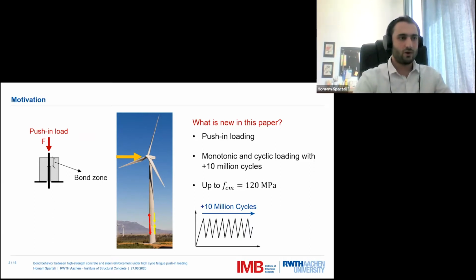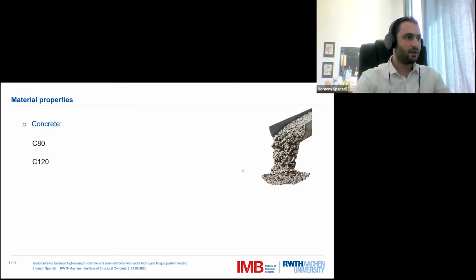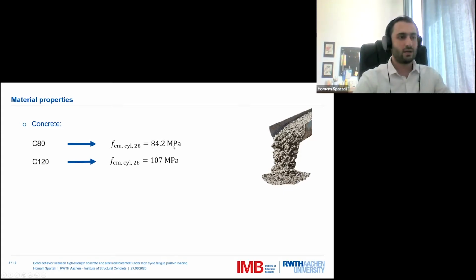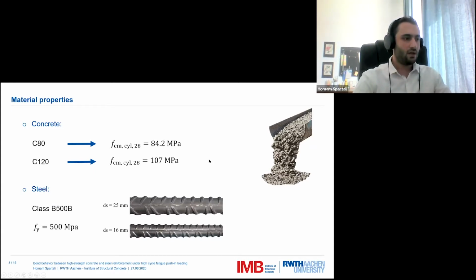Now let's see the ingredients of our specimens, namely the material properties. We use two classes of concrete according to the fib Model Code. These are the C80 and C120. According to the material tests that accompanied our push-in specimens, we obtained the values 84.2 megapascal and 107 megapascal for the first and second concrete class respectively. Regarding steel, we used the class B500B with a tensile strength of 500 megapascal, and we used two different bar diameters: 25 millimeters and 16 millimeters, which are also ribbed bars.